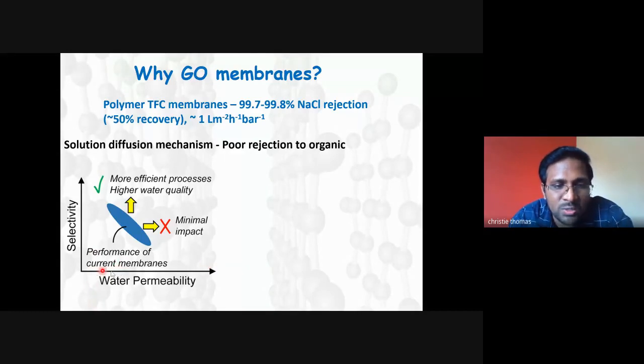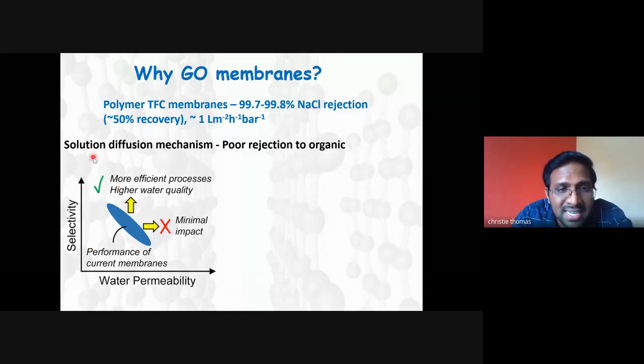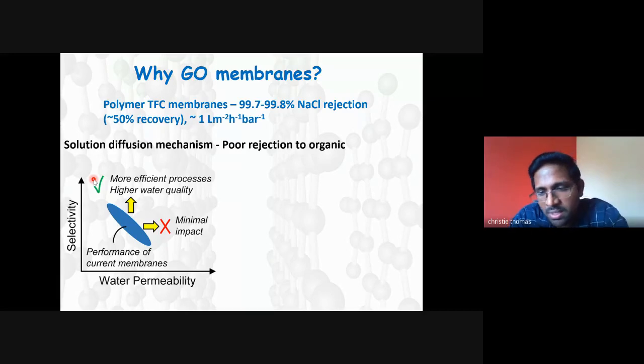So you can see that as water permeability in typical membranes increases, the selectivity goes down, which is a kind of trade-off. In a typical polymer membrane, when water permeability increases, selectivity goes down. But in graphene oxide membrane, you can get selectivity as well as high water permeability at the same time. You can see a tick mark here. Okay, so GO comes here. It has higher selectivity as well as high water permeability.